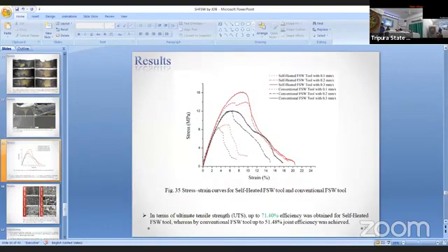So here also you can see, if we look at the stress strain curve in terms of UTS, 71.4% efficiency was obtained for the Self-Heated FSW tool, whereas when we use the conventional FSW tool for the same material with the same parameters, we could achieve only 51.48% joint efficiency. So with the help of this Self-Heated tool, we could achieve a better joint efficiency.